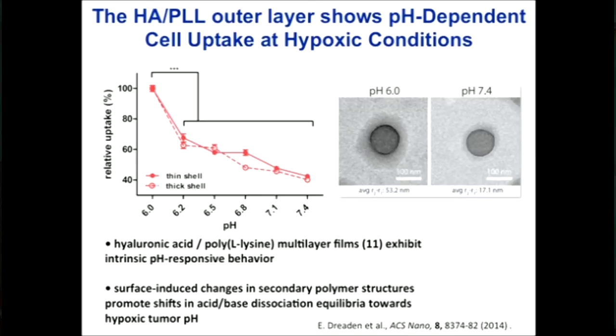So here we're looking at relative cell uptake. And at pH 7.4, it's low, and it jumps up as we go to lower pHs. So in a hypoxic environment, we can actually get much more cell uptake. That means that we can have this nanoparticle going through the bloodstream. It's not really engaging anyone or anything. But when it gets into the tumor, it becomes sticky. And that's what we'd like to do.